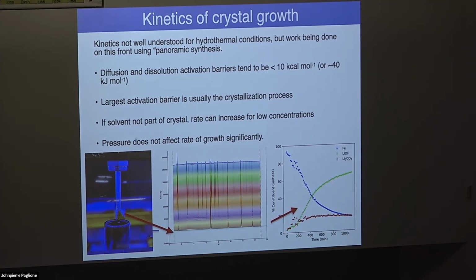So again, this is a more detailed example of doing in situ X-ray diffraction at 17-BM, where we actually have all the different patterns. And you can see here you have different peaks that are showing up as a function of time increasing, these are all just different scans. And once we do the Rietveld refinement, we can see our iron concentration is going down, our lithium hydroxide intercalated iron selenide phase is increasing, and we also have some lithium carbonate impurity that does start to form, but then levels off. So once you have this sort of data, you can go a little bit more in depth and think about the kinetics of how your compounds are actually being formed.